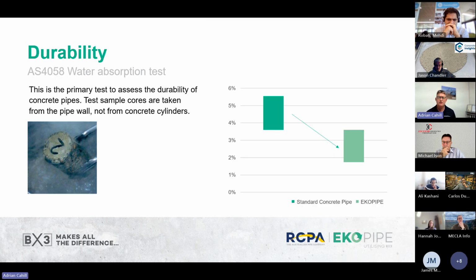From a durability perspective, concrete pipes are quite unique in that the only durability test is what's called the water absorption test. This is, for those in Victoria, very similar to a VPV test. One of the key differences is that the sample is actually taken from a cast pipe. So we cast a pipe. After 2 weeks, we'll then extract cores out of that pipe, and then they're taken to a test laboratory and undergo a drying phase. And then they are boiled for 5 hours at 100 degrees, and you measure the loss and gain of water through that process.